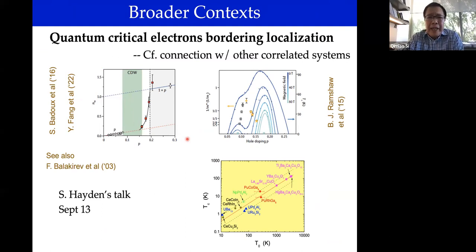One is that it appears to us that with the lessons we've been learning about the nature of the normal state, the quantum critical state with strange metal properties, and its effect on superconductivity could have connections with what's going on in other classes of strongly correlated systems. So, for instance, in the cuprates in 214, there have been recent experiments that provide evidence for a Fermi surface reconstruction near the quantum critical point, the existence of a quantum critical point, or at least not too far away, the system in the optimal doping regime not being too far away from a quantum critical point.